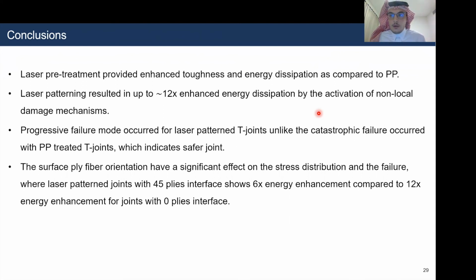Finally, the ply orientation on the surface has a significant effect on the stress distribution and the failure mechanism, such that the T-joints that were patterned with 45 degrees on the surface showed 6 times enhancement in the energy, while those patterned with 0 degrees showed 12 times enhancement in the energy.